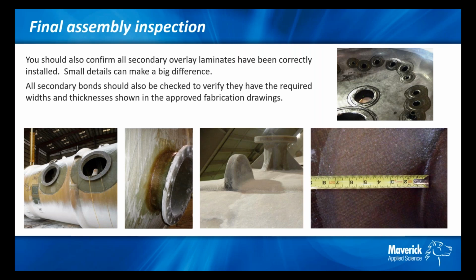Those attachment laminates are installed incorrectly, though. The fabrication drawings showed the laminate should have continued up the tailing lug surface and bonded on to a thinner 1/4 inch starter plate and then be trimmed. This mistake could have resulted in employee injury during lifting or damaged equipment.